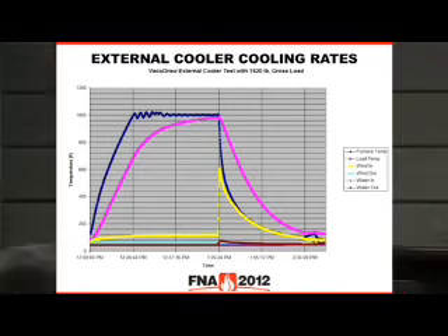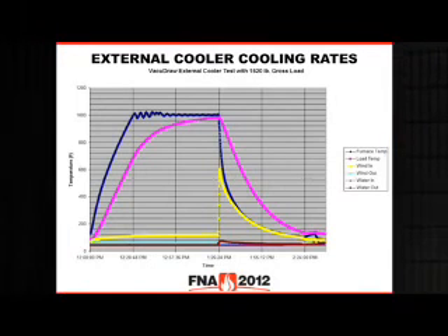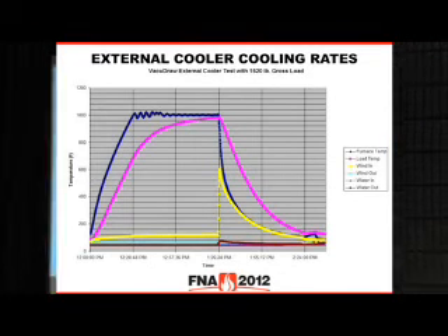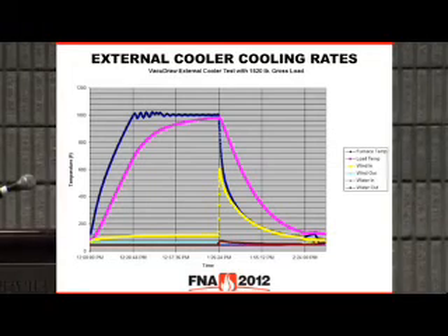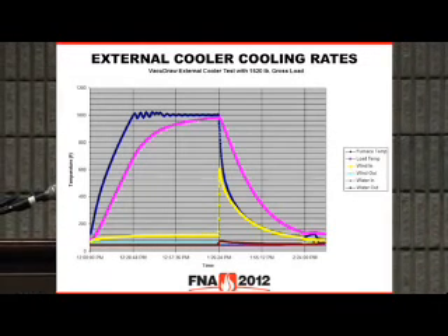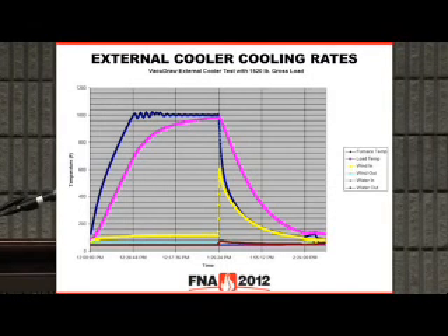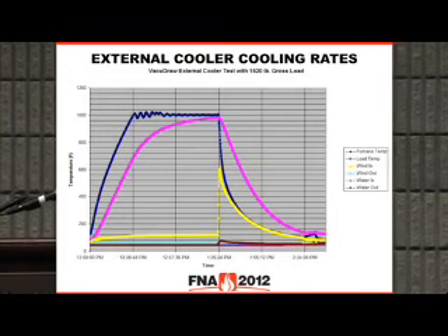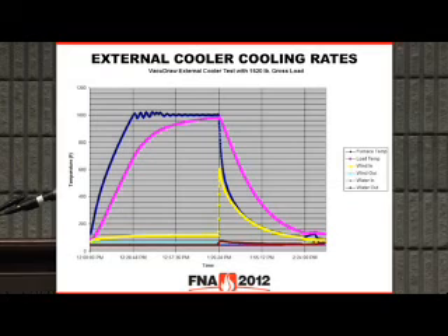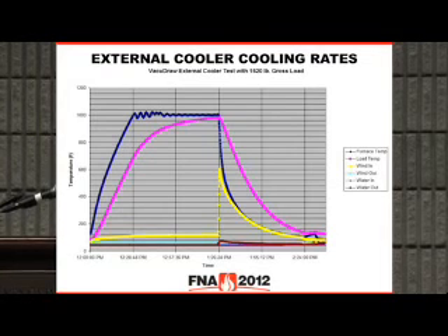This is a closer example. This has also got some load couples and shows you the comparison between wind temperature and load temperature. So again, this was a 1,500-pound gross load. We soaked it at 1,000 degrees. In this particular application, the customer said once the load couple or the buried thermocouple reached 1,000 that the soak was complete. We then start the cooling, and the yellow line is basically showing wind temperature or furnace temperature, and this is taking roughly 30 minutes to get down here.